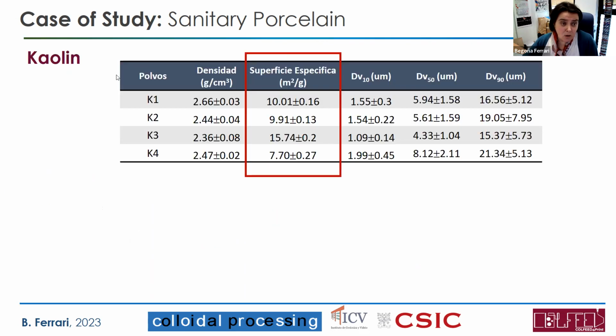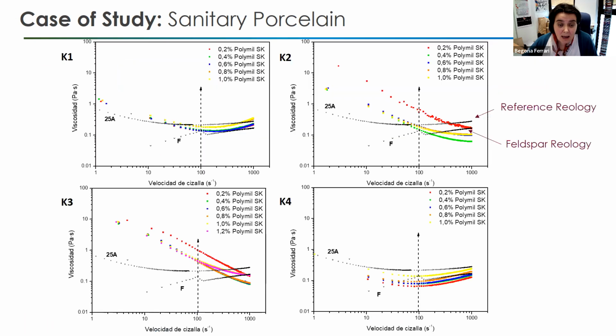And for example, if we are going to examine different kinds of powder, in this case, different kinds of kaolins that have more or less the same specific surface and more or less the same particle size, we cannot say which kaolin is better or not. We can go to the rheology, right? And we can fit our suspension or dispersive suspension of kaolins with the rheology of the mixture. And you can see here that all the suspensions of kaolin are fitting the rheology of the mixture.